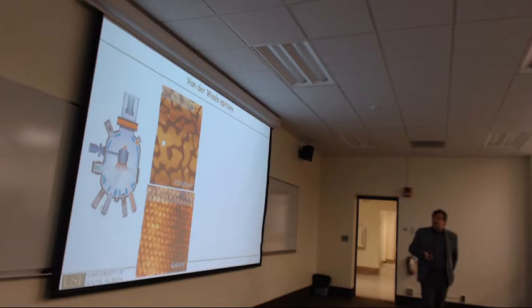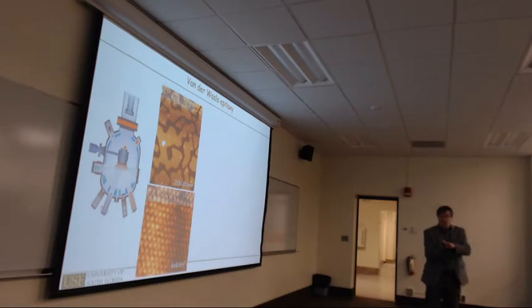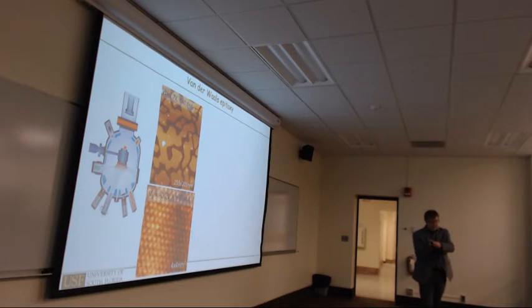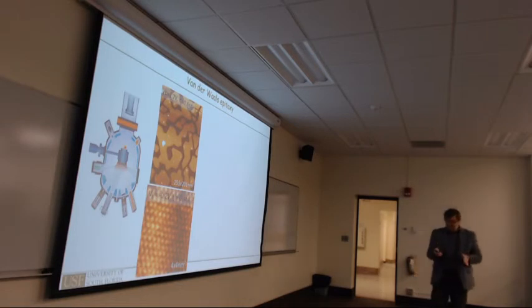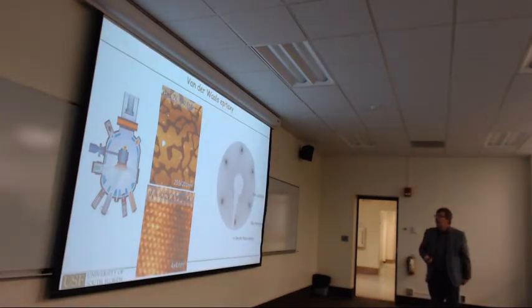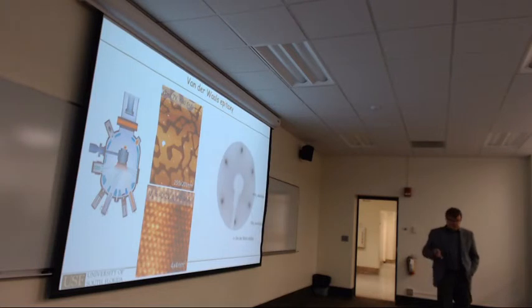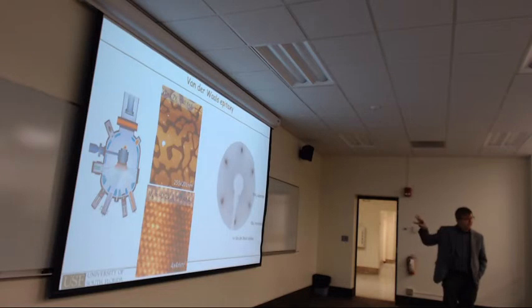But the one important point I want to make is, although you grow on a van der Waals substrate, the grown film is rotationally aligned with the substrate. And the best way to see that is from electron diffraction, where here now you have two van der Waals materials on top of each other. So you get two sets of diffraction spots, one from the substrate and one from the film.